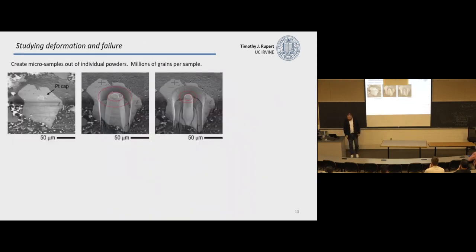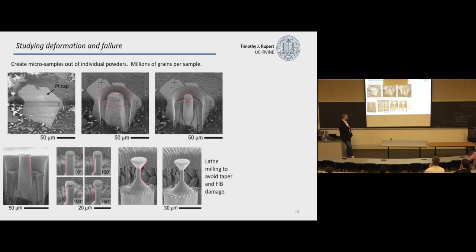Because we're interested in mechanical properties, I want to jump in and look at some mechanical testing. We've done lots of different types of tests. I just want to show you these in situ SEM tension tests we've done. We can either do it on a bulk sample or even on a small particle of this material. We make something that looks like these micro compression pillars, but then we also mill around and leave a little gauge or a little grip section at the top so that we can pull on this.